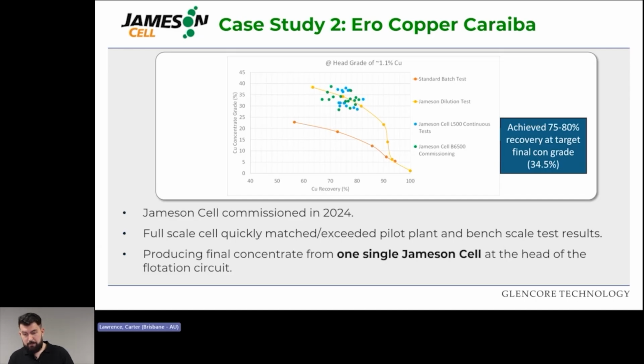So very quickly, we were achieving 75 to 80% recovery at that target final concentrate grade of 34.5% from that single Jameson cell. And that basically completed the debottlenecking project for Caraiba.